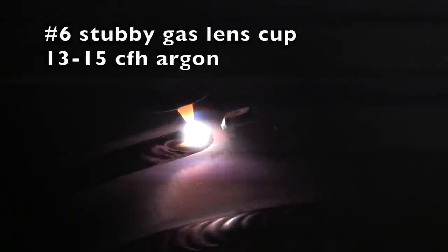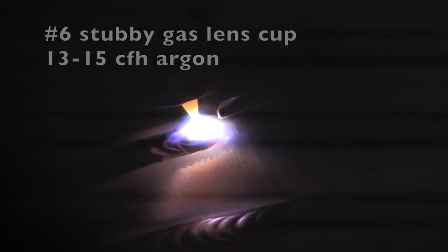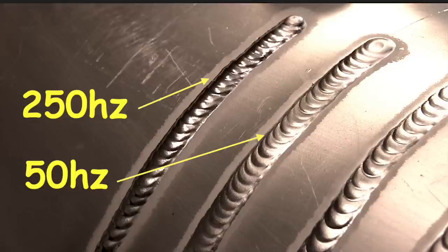It's going to narrow the bead quite a bit. Notice that the tip on that electrode is staying really sharp, almost like I was welding steel. But it's welding a very narrow bead, which is a very desirable thing sometimes. But if you just want penetration and you want heat input, the most heat input you can get at a certain amperage, which on a 200 amp TIG welder, sometimes you need all you can get out of that max amperage.